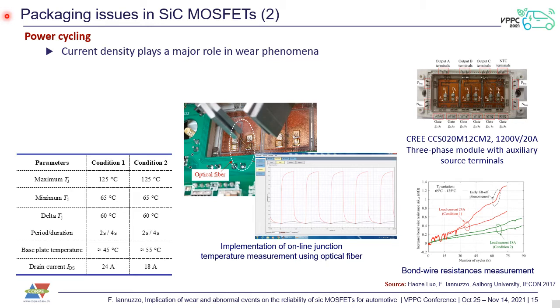Some experimental results point out how critical this current density through bond wires could be. In this slide, you can see some experiments which have been conducted at Aalborg University, where we simultaneously cycled components under power cycling and measured the temperature swing through optical fibers. In this table, you can see the maximum junction temperature, minimum junction temperature, temperature swing, and cycling period for 2 conditions, condition 1 and condition 2, which only differ in the drain current. The way we obtain this is to use a different gate voltage for the 2 cases, in such a way that for the higher current we get a lower on-state voltage, and the other way around, in order to keep the power dissipation constant.